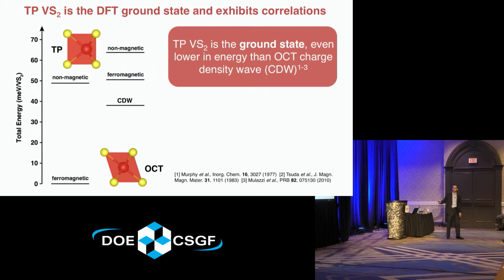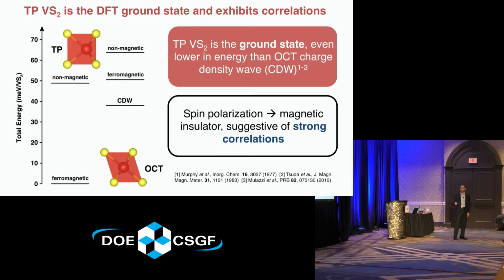But the important thing here is that if you look to the left on the trigonal prismatic side, you can see that the lowest energy state is actually trigonal prismatic. So this is the phase that doesn't yet exist, but we actually find that it's significantly lower in energy than the octahedral. So already this is promising that this thing should be able to exist. We find it's thermodynamically stable. Furthermore, this trigonal prismatic compound, you can see within DFT, has a strong magnetic instability. So we find what's called a ferromagnetic ground state. And the magnetism in this system is so strong that even within DFT, already it fully spin polarizes. So we already have an insulator even at the level of band theory. So that's a strong indication that we have signatures of strong electronic correlation.